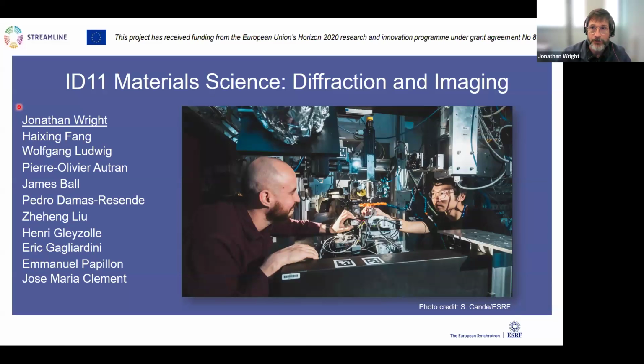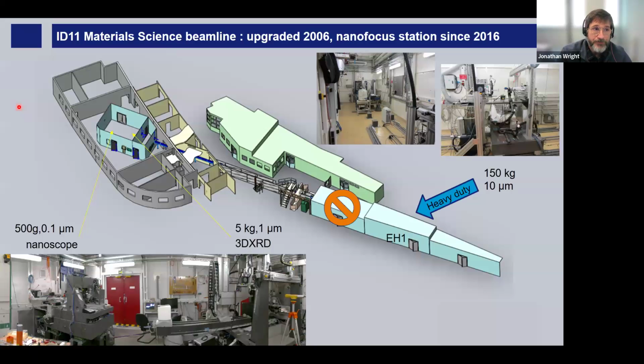So the first thing I wanted to try to do is to give you a quick virtual tour of the beamline. ID11, as Tilman said, was one of the first beamlines at ESRF, and so this optics hutch here, OH1, was one of the first hutches on the experimental floor, and now it starts to show its age a little. The next piece of beamline that was built was this EH1 experiment hutch. What this is used for today is large heavy duty sample environments. So in this hutch, there's a nice big space where you can bring in sample environments. And the great advantage here is you can come in and do experiments that might not fit somewhere else. The limitation is we don't have the highest spatial resolution. It's only about 10 microns, but you can have 150 kilos.